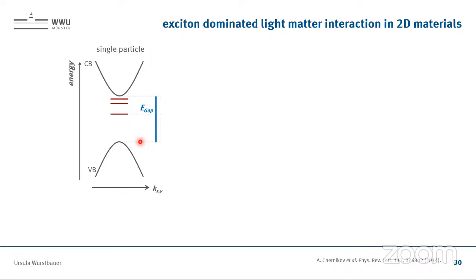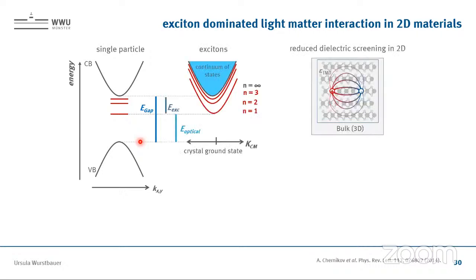If we have these excitonic signatures on top, meaning if we have a binding energy and internal energy attached to it, then it appears as if there would be some in-gap states which are not there. It's not a real state, it's, let's say, a virtual concept, because this energy from the single particle states is reduced by the exciton binding energy. So meaning in optical emission, or also absorption, we see this optical energy here, which is the band gap reduced by the binding energy.